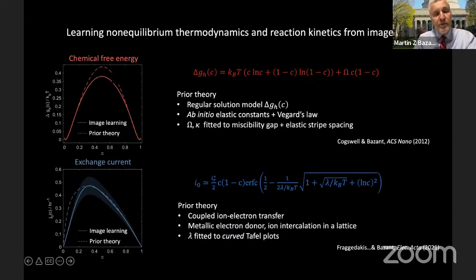And just for comparison, in this case, the dashed line is the function that I had been previously using, which is the so-called regular solution model. That function is given here in red. And you can see it's reasonably close, but the barrier shape and height is a bit different from what we learned. But to me, much more interesting actually is the measurement of the reaction kinetics, or exchange current versus concentration. And here we see that the learned model, which is the solid line, is extremely close to the prediction of that coupled ion electron transfer theory I showed you.